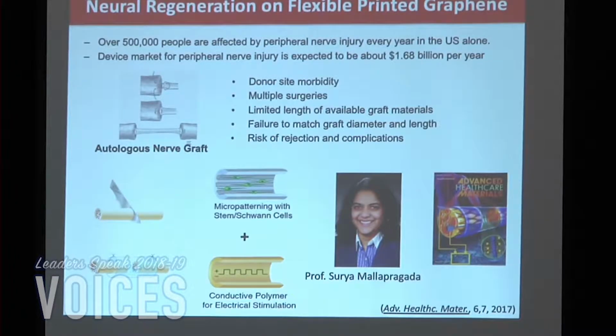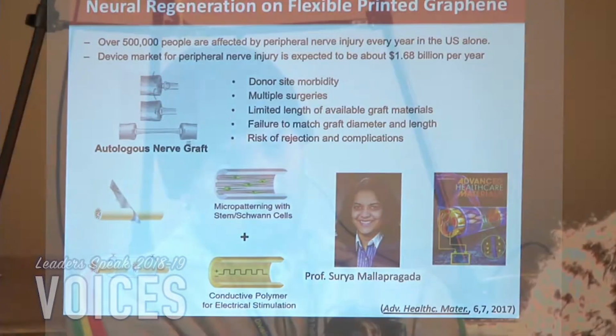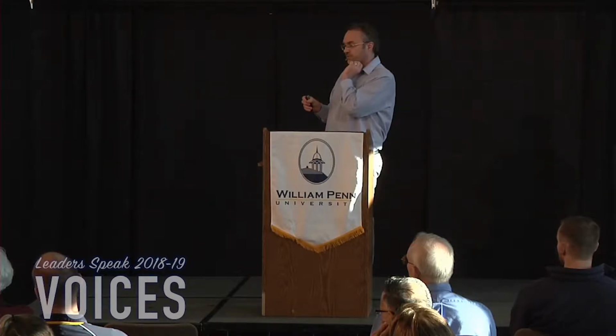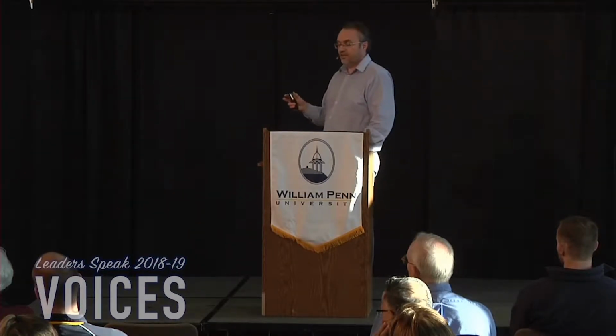But now we've also used that same graphene that we've printed onto different substrates in that kind of finger comb-like structure, the interdigitated electrode. And since it's just carbon, it's very biocompatible. So we can actually grow cells on these circuits, and they like that surface too, because they like that rough microstructured surface. And we can electrically stimulate them so that if we put stem cells on them, they can transdifferentiate into different lineages. So this was a case where we teamed up with a collaborator at ISU, Prof. Surya Mallapragada, to make these kind of nerve conduits to embed nerve cells into breakpoints of a nerve, peripheral nerves, and hopefully help regenerate that nerve.